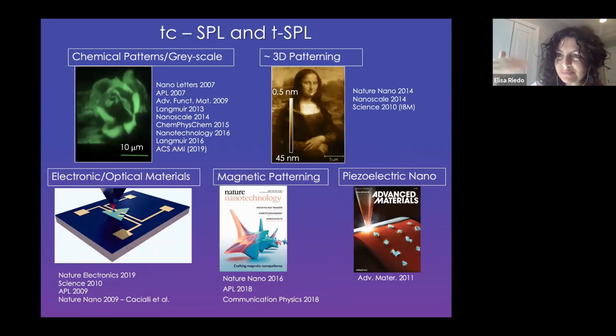I must say that sometimes I myself also use tCSPL, because now everything is becoming so broad that it doesn't really make sense to keep two names. So tSPL and tc-SPL may be used interchangeably, but let's try to stay focused for this seminar on the idea of the thermally activated chemical reaction. So far in my group, we have demonstrated the possibility to use a polymer and then activate the chemical reaction, expose some functional groups, and then use these functional groups to attach other molecules like proteins or enzymes, and also to create chemical gradients of these biomolecules.